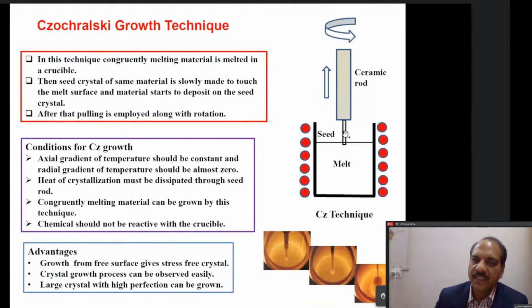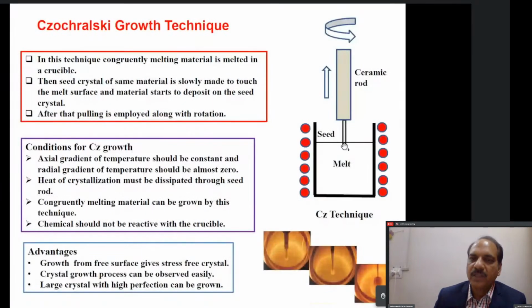Basically, pull the seed up very slowly, and you will see that slowly the crystal starts at the tip of this seed. And then depending upon the rotation rate and the pull rate, the size of the crystal is decided. So we call it necking, and then we call it shoulder, and then finally we get an almost uniform crystal. And once the crystal has been grown, then finally again raise the temperature slightly, so that the final interface region melts and the grown crystal is detached from the melt, and we take out the crystal.